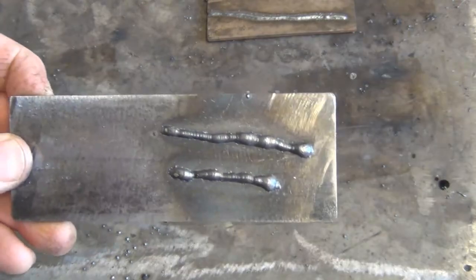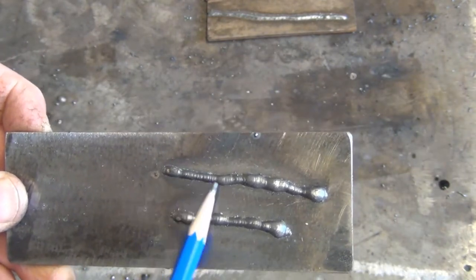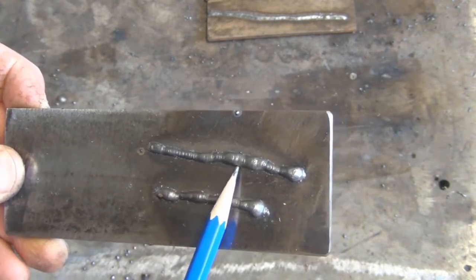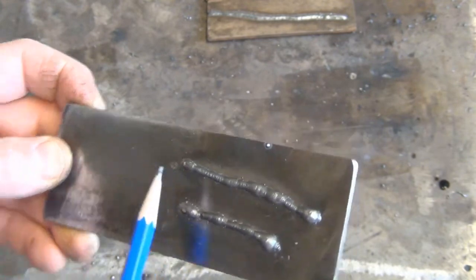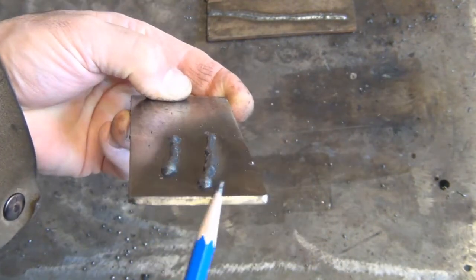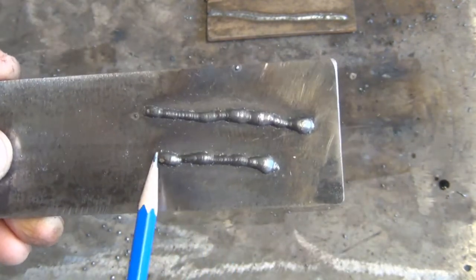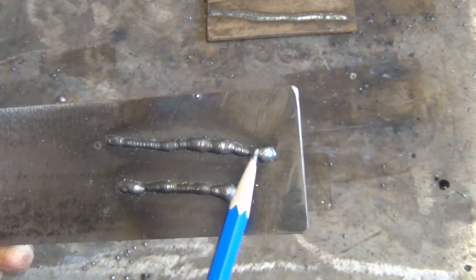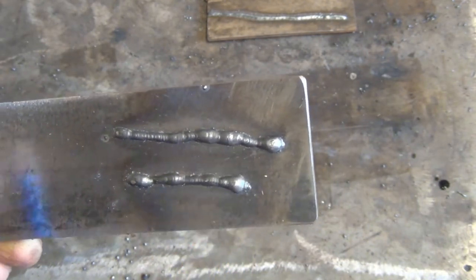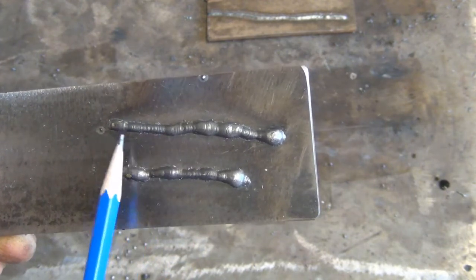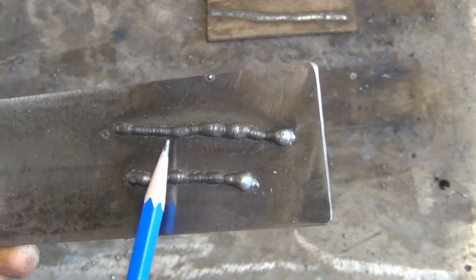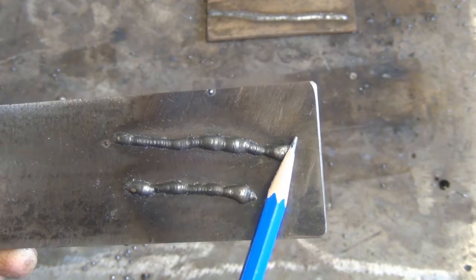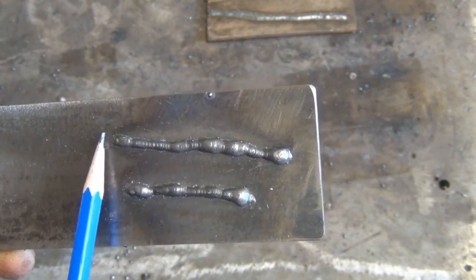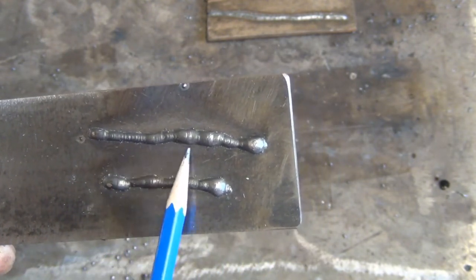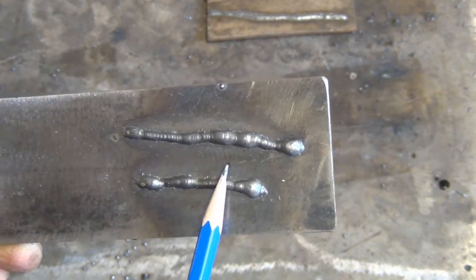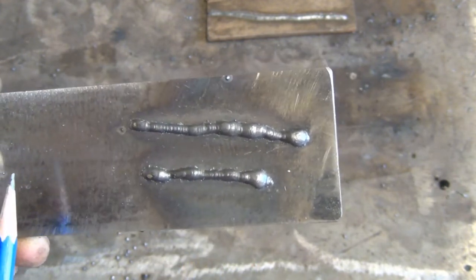Number two. Okay, I look at this and I can see that this is what we call ropey. You can see it just looks like a rope. Okay? That tells me one thing. Not enough amperage, not enough heat. I can qualify that with the fact that there's no splatter around it. It's just a wet piece of rope. So in this case, I'd bump up the heat. Try again.